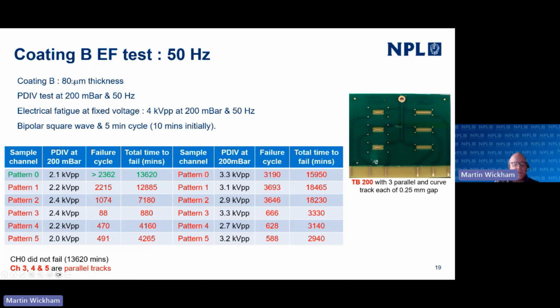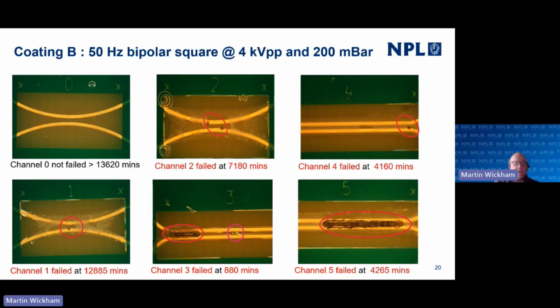So you might expect these total times to be 20 times what the first system was. In this case, actually, we've got a slightly thicker coating at 80 microns and the same bipolar square. You can see here that we've got parallel tracks as well as curved tracks, although there's the same gap between them. And again, particularly in the curved tracks, we're not seeing failures at the highest voltage, and we're not seeing failures in the parallel tracks in the same position on the tracks all the time.